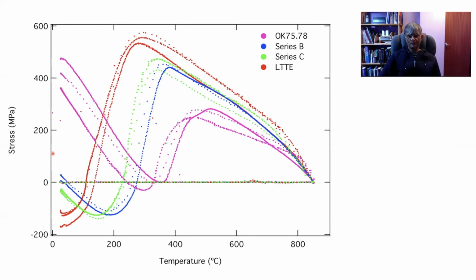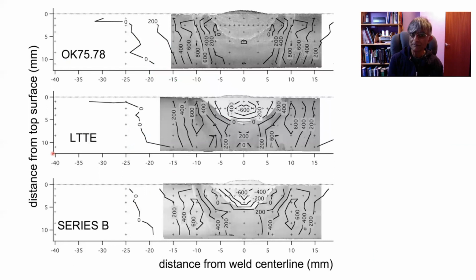How do we prove that this actually works in a welded joint? And a welded joint is much larger than the sort of specimens being studied here. So we need a diffraction technique which can penetrate a lot more material than X-rays or synchrotron X-rays. And of course, that technique is neutrons. So you go over to a neutron facility, and this particular experiment was done at Chalk River in Canada, where this is the control welding alloy, and these are the low temperature transforming alloys.